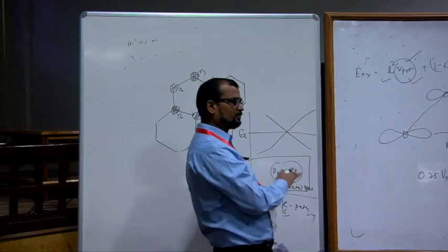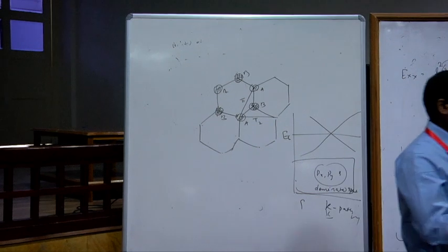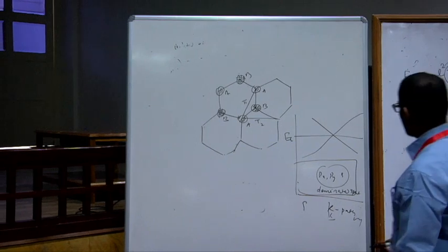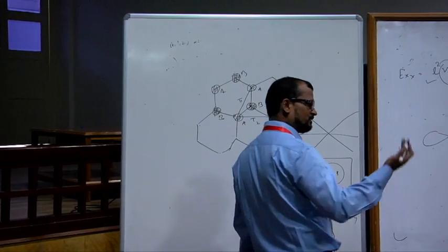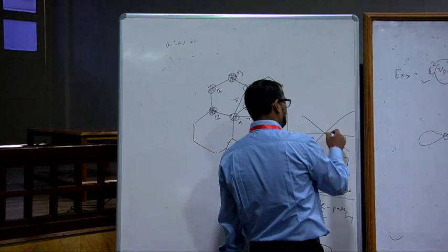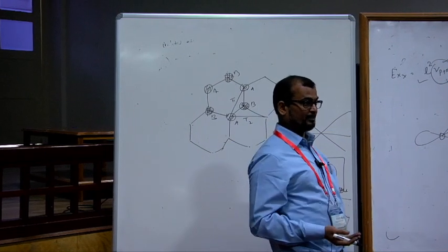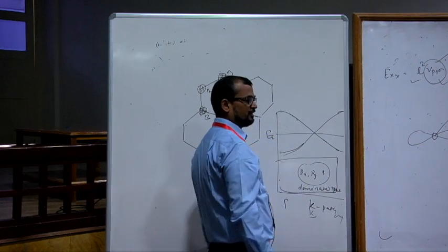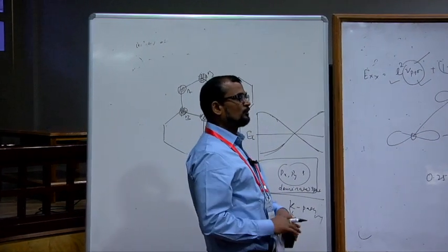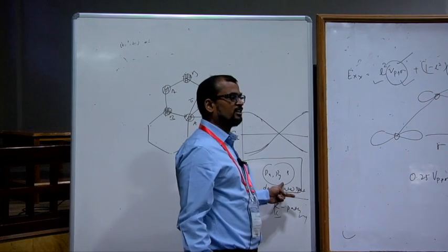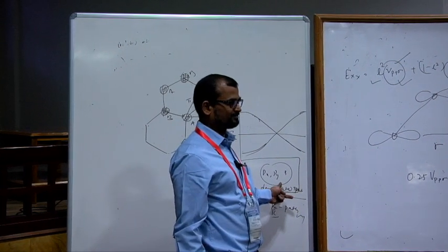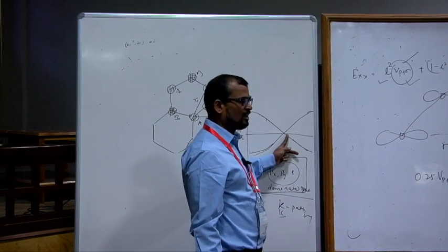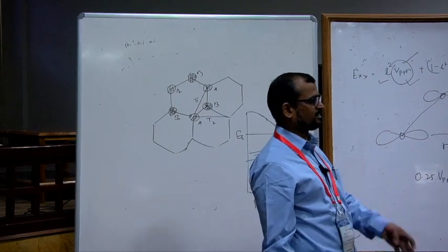Far below are the bands dominated by the planar orbitals, Px and Py, due to the sp2 hybridized states. But we see that the properties of graphene are actually defined by these linear Dirac bands. Out of curiosity, I am less interested in studying the bonding of those states, because all my properties I am extracting from here, unless you study defect states like magnetism.